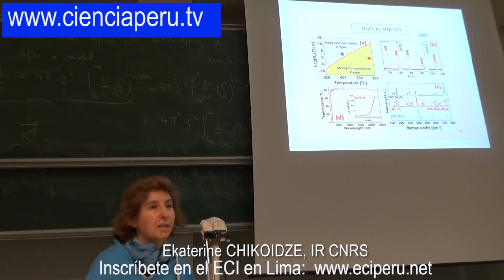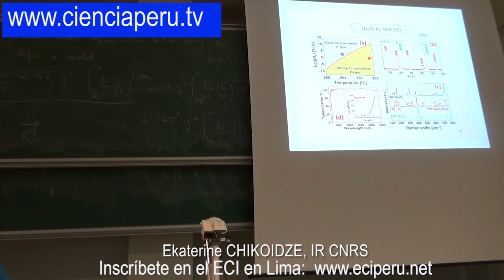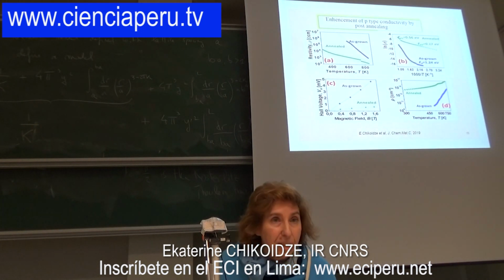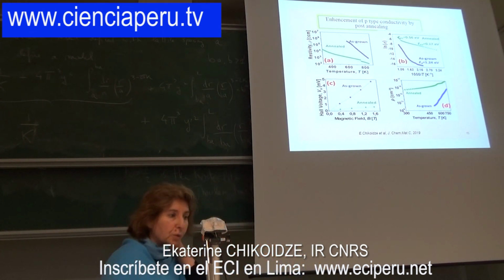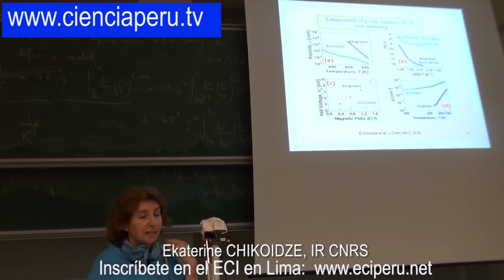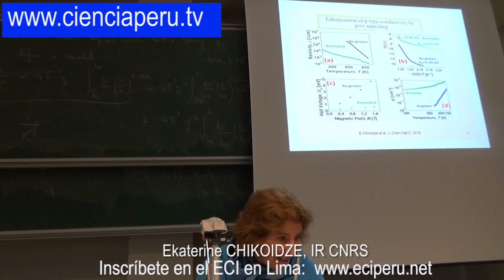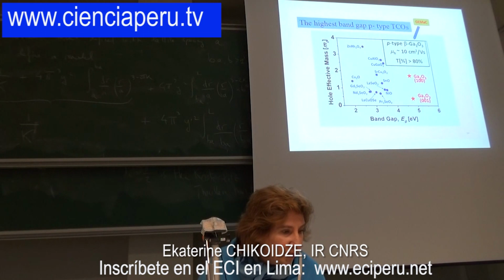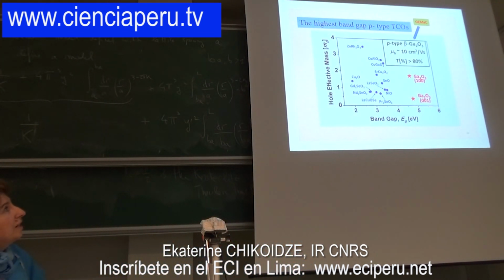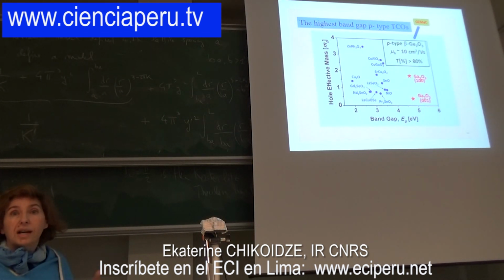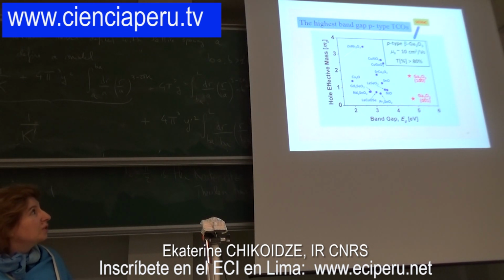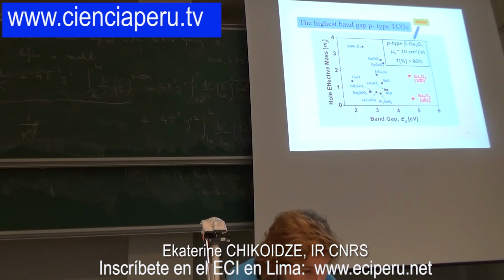And of course it was very interesting to reproduce this by another method, and it was done at GEMaC in Versailles by his colleagues, and we were very happy to find that the samples are of very high quality and also exhibit p-type conductivity. We also made post-annealing to increase conductivity, which is a very important step for the realization of devices. To give you an idea of where gallium oxide sits, what is important is not only to be p-type, but also that mobility is high. When I say high, I refer to other oxides which have below 1 or 2 mobility, and gallium oxide fabricated in GEMaC has around 10.